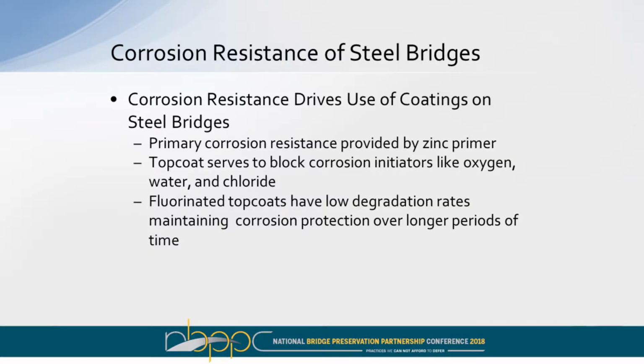Most people are putting coatings on bridges for corrosion resistance. The primary driver of corrosion resistance is really the zinc primer. It corrodes preferentially to steel if the coating is damaged. The top coat serves to block corrosion initiators like oxygen, water, and chloride. Because fluorinated materials have lower degradation rates, that means they're going to be around longer to help keep these materials from reaching the zinc primer. So that's the main advantage to these.